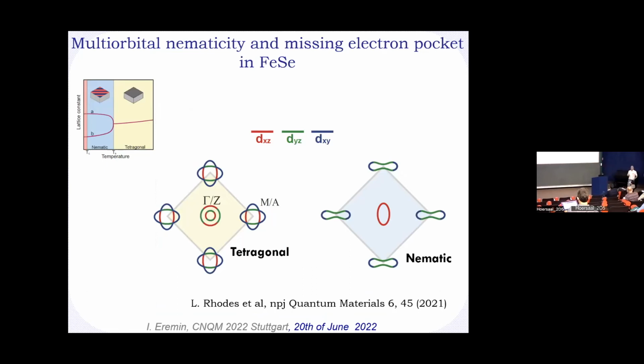The reason is that in iron selenium, we don't know exactly the structure of the nematic order. However, what we know very well is how the electronic reconstruction takes place. And what is known is that if you start from pure iron selenium, there are four Fermi surface pockets with a corresponding orbital spectral weight. And once you go into the nematic state, the Fermi surface is also well characterized. Its orbital contributions are well known. It basically consists of a single orbital of XZ character, a hole pocket near the gamma point, and an electron pocket, which is orthogonally oriented with respect to the hole pocket, and basically a mixture of the YZ and the XY pocket.